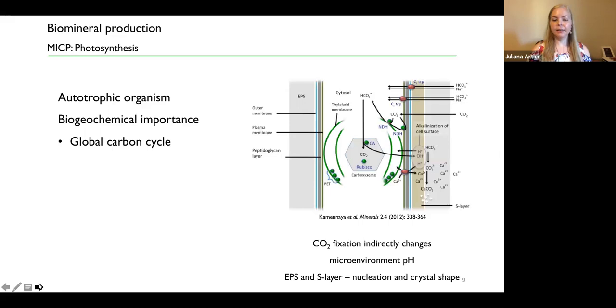They are also studied in the sense of the biogeochemical importance, because they have an important relationship to the global carbon cycle from different geological periods. And the way this photosynthesis would be important to change the pH in the environment is that the cells capture the energy from sunlight and use that for fixating CO2 here in the carboxysomes. During this process the cells also send a hydroxyl group to the outside to balance the ions here. And with that, it alkalinizes the cell surfaces. Again, with the increased concentration of calcium, the cells are able to indirectly induce calcium carbonate precipitation.